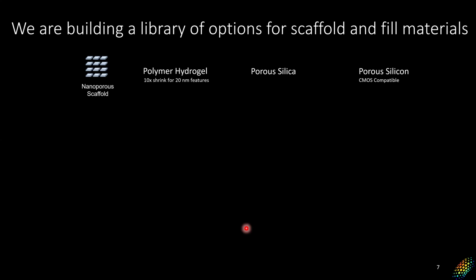So I talked mostly about silica and polymer, but we're actually building up a library of different options for scaffold and fill materials. In addition to porous silica, we can also do this process inside of a polymer hydrogel, which you can think of as a nanoporous polymer structure or scaffold, which you can then dehydrate and shrink down by a factor of 10 or more. And that's what gets you tens of nanometer resolution, if that's necessary. In a lot of cases, we haven't found that's necessary. On the other hand, you can directly porosify a silicon wafer and then fill in materials in the silicon wafer. So this can also be compatible with traditional wafer scale processes.